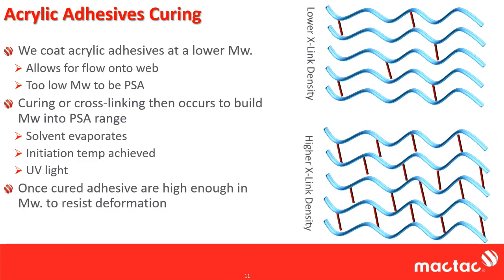How we get around that is adhesive curing, or what we call cross-linking. What we do here, and this is mostly for acrylics, and with the acrylics, I'll be covering in this section really the solvent-based and UV cured acrylics. They are the ones that cure. And this is the fundamental difference between acrylics and rubbers.